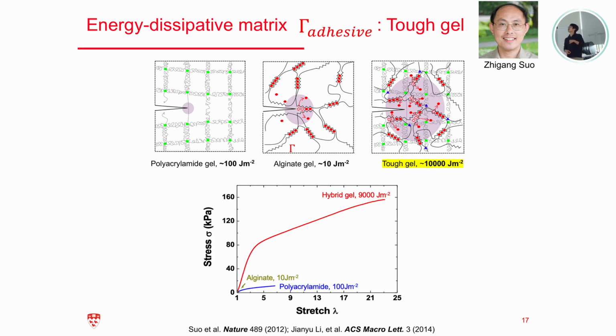And those are the technical details of how we make it possible, right? First of all, we need to use a very tough and dissipative matrix. So our strategy here is to use tough hydrogels. There is significant research effort in the field to try to make the hydrogel very tough, very stretchy, and also, as you can see, the area underneath will be very large, indicating it dissipates a lot of energy. And this system is represented by this combination of polyacrylamide and alginate hydrogel. As you can see here, this gel matrix is very tough and also very stretchy.